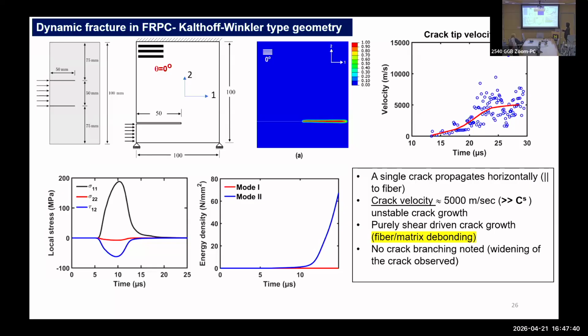So again, for the 0 degree case, we see that there is one single crack that propagates horizontally. If we look at the energy spectrum or the local stress behavior, we will see that it is purely shear driven, or mode 2 driven, crack growth. So again, fiber matrix delamination is the known dominant mechanism for this 0 degree lamina.